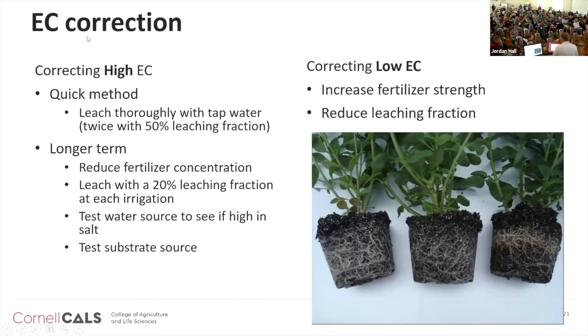And then EC correction. If we have a high EC, that means that we're either over-fertilizing or our water source or substrate is high in salts. So a quick method is to leach thoroughly with tap water so that we get about a 50% leaching fraction, so about half of the water that you add to each pot is leaching out of the bottom, and do that twice. That's going to reduce the EC by about half. The longer term control would be to reduce your fertilizer concentration and leach more frequently with a 20% leaching fraction, so just do that periodically. And then test your water source to see if it's high in salts, or test your substrate source to see if it's high in salts, to try to identify the cause.